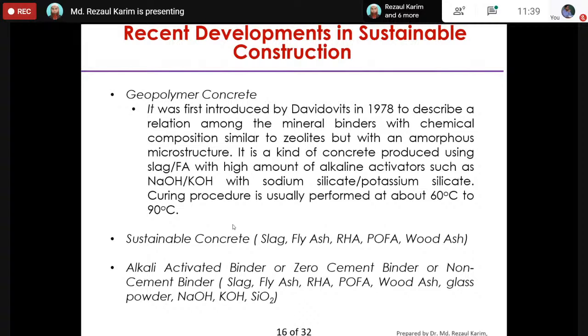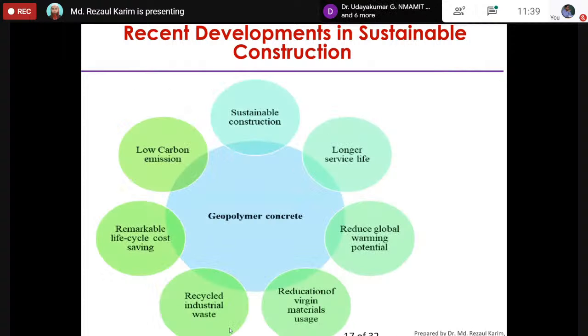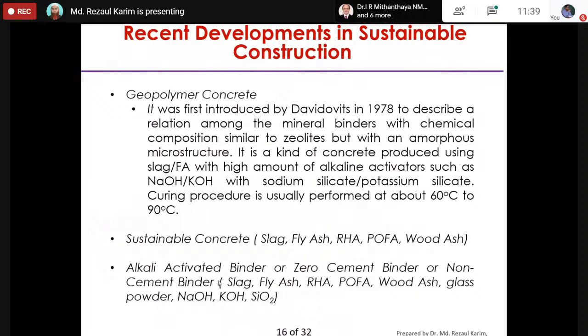Now we'll move towards recent developments in sustainable construction. Geopolymer concrete is one of the latest developments. Although the term was introduced by Davidovits in 1978 to describe a relation among mineral binders with chemical composition similar to zeolite but with an amorphous microstructure. It is a kind of concrete produced using slag or fly ash with a high amount of alkaline activator, such as sodium hydroxide and potassium hydroxide, and silicates such as sodium silicate and potassium silicate. Usually in geopolymer concrete, the curing procedure is performed at about 60 to 90 degrees.